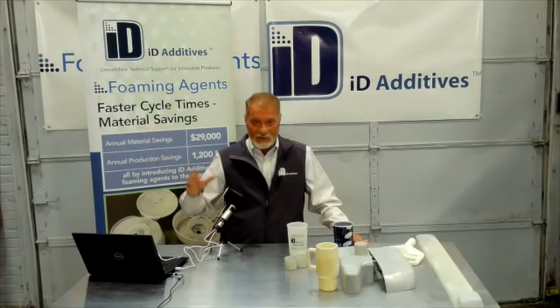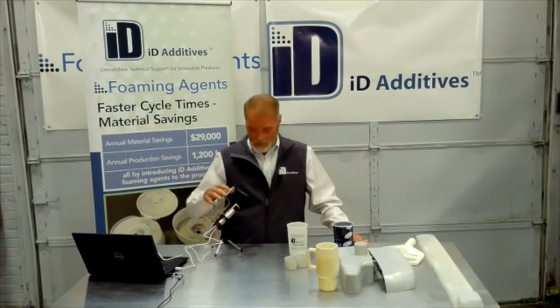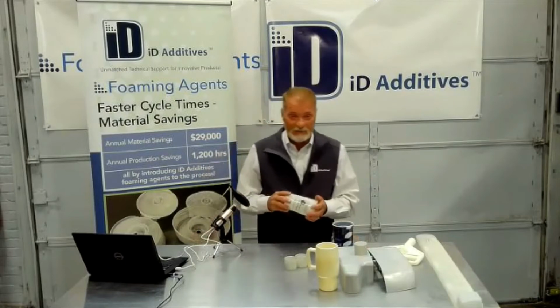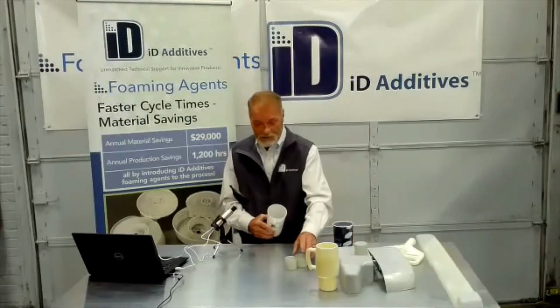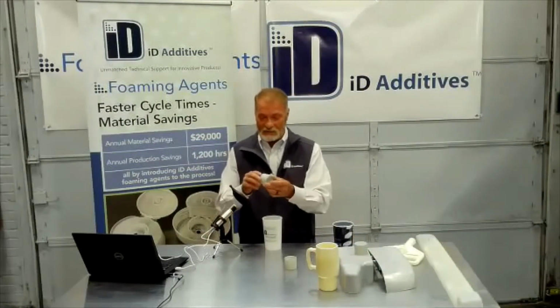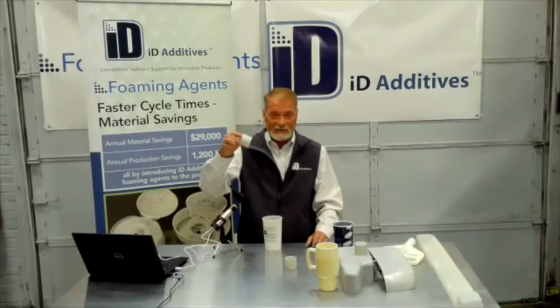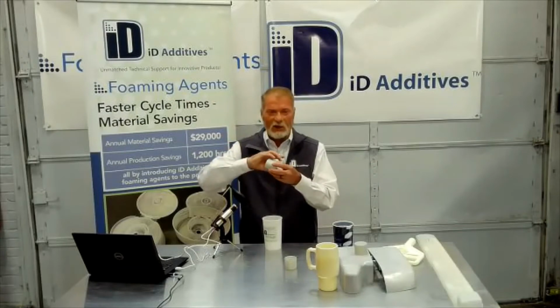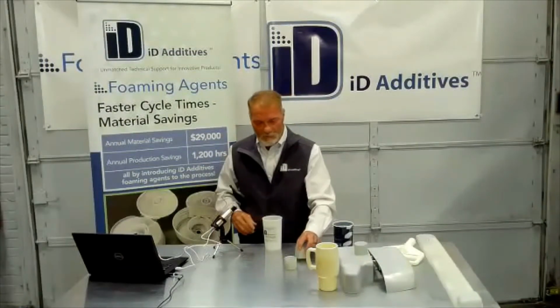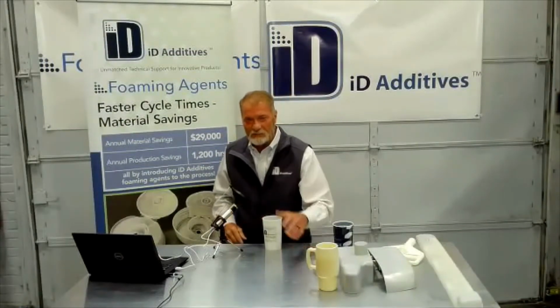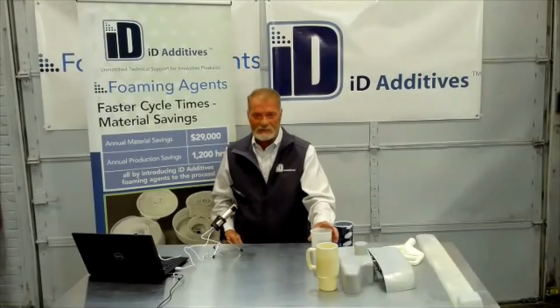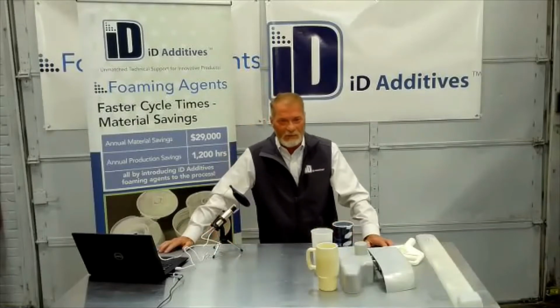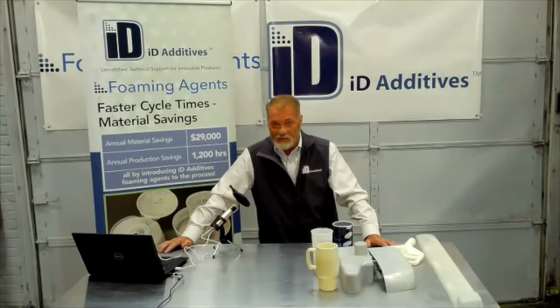The faster, the lighter. The faster, the more aesthetic it'll be. This cap right here is a 28 thousandths wall, and it is highly aesthetic. There's no splay anywhere on that part, and the bubbles are loaded in the wall. So yes, we can do very high gloss, Class A surfaces, and if you add any color, you'd never know it was there.